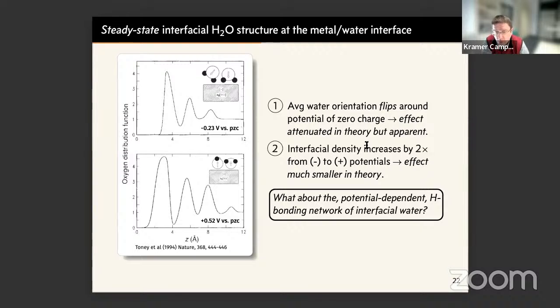This paper was from 1994. It's clear now from a variety of increasingly complicated theoretical studies that this effect is apparent in theory, but significantly attenuated. One really has to average over all sorts of fluctuations in order to see this. If you integrate under these curves, one would infer that the interfacial density increases by something like a factor of 2 as one goes from negative to positive potentials, so that in this oxygen-down configuration, the first layer is much more dense. This effect, if it exists in theory, is much, much smaller.